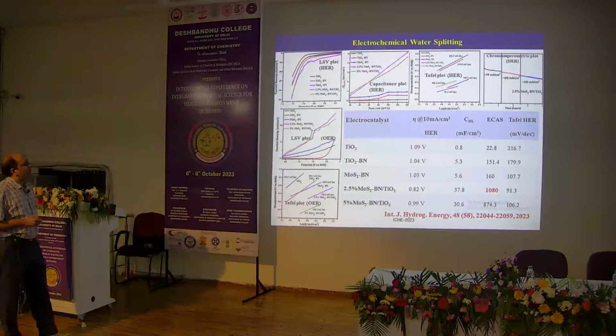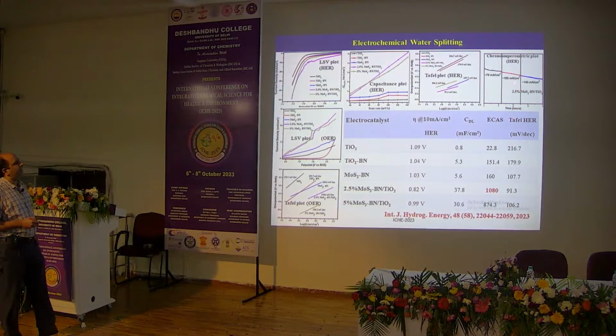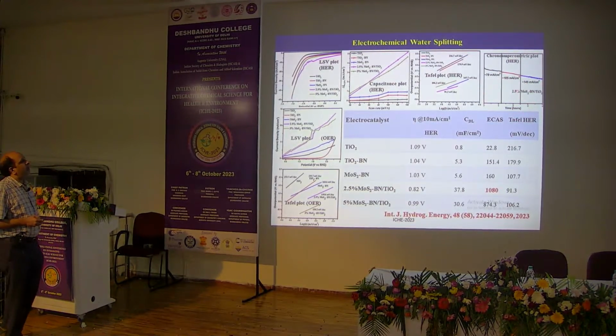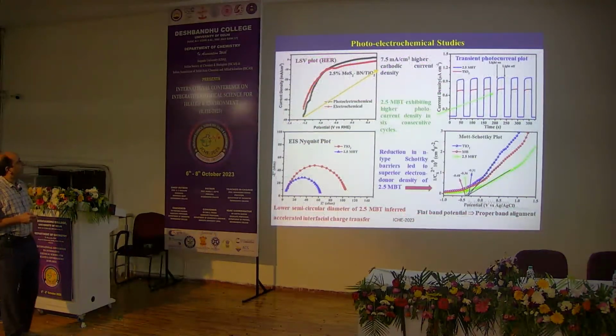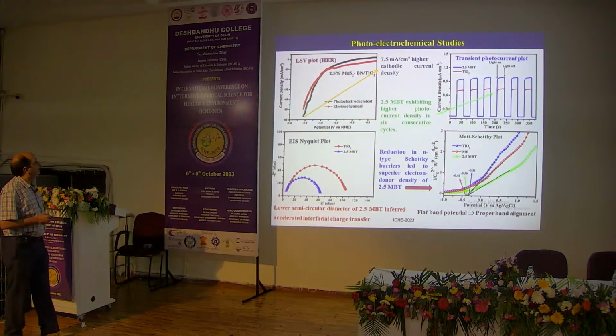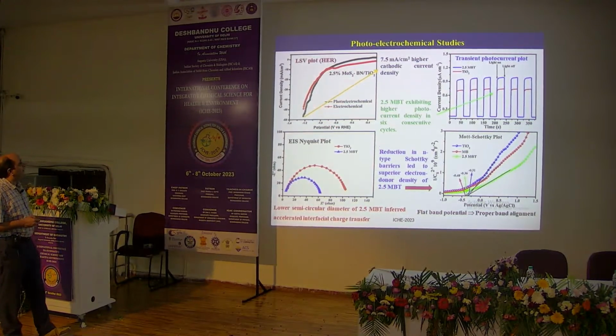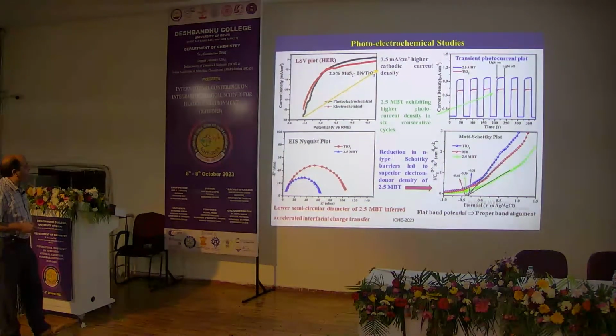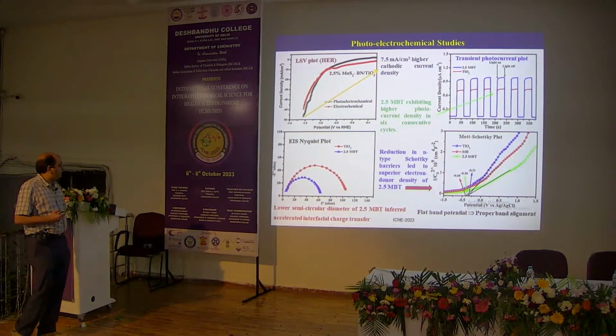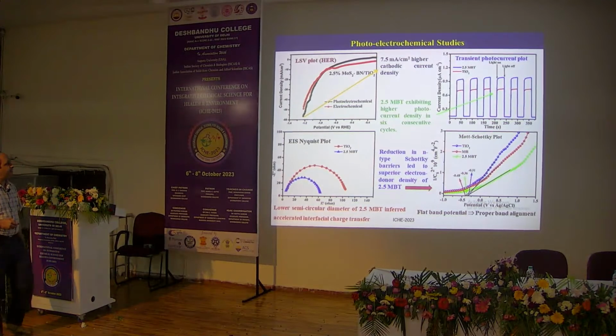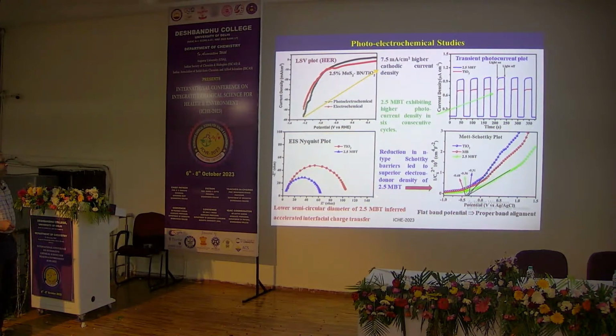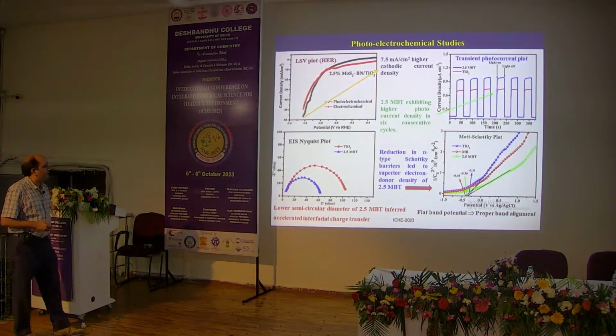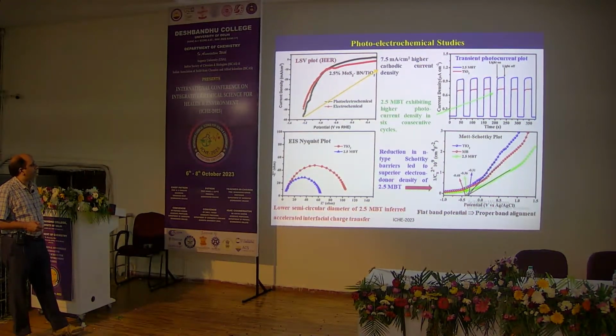And if you see the chronoamperometric plot, then it shows that in a 4 hour time the HER reaction could become doubled. This is the photoelectrochemical investigation, and it shows that this 2.5 MBT could generate 7.5 milliampere per centimeter square high cathodic current, and this is the EIS plot, and the lower semicircular diameter of 2.5 MBT could lead to the accelerated interfacial charge transfer, and this is the transient photocurrent plot for 2.5 MBT, and it shows the stability up to 6 consecutive cycles. And here this is the Mott-Schottky plot which shows the proper band alignment in our as prepared 2.5 MBT.